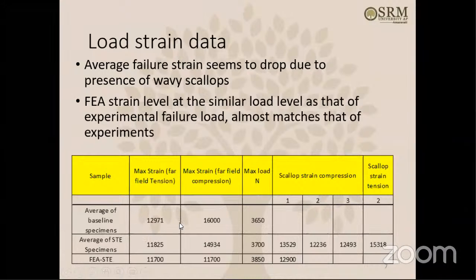As you can see, the load is similar. But under similar loading, we compare the baseline coupons and the STE coupons, that means sculpted trailing edge, the wavy feature coupons. These are the strain levels that can be seen. The wavy coupons are failing at a lower level of strain compared to the baseline. Here also, as you can see, and FEA strain levels are also shown here.